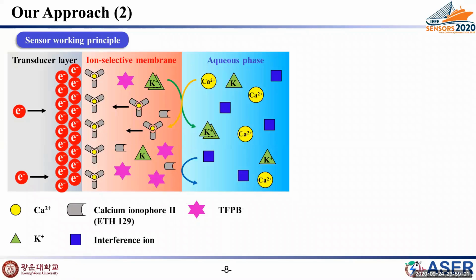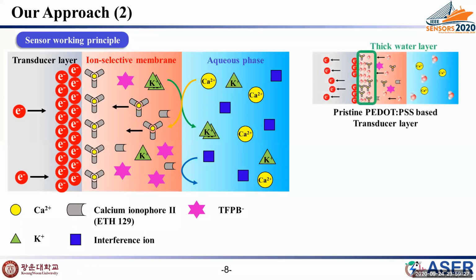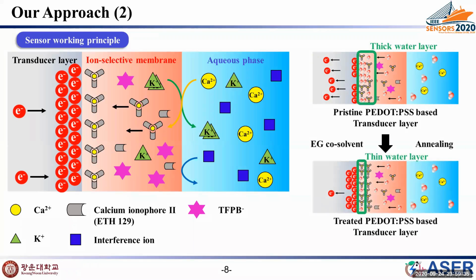I will briefly introduce the working principle of the sensor. The calcium ions in the analyte and the potassium ions in the membrane are exchanged at the interface between the ISM and the analyte. Then calcium ion forms a complex with the calcium ionophore and moves to the transducer layer. At this time, an electric potential is formed across the total ISE, and the potential difference with the reference electrode is output. After that, a water layer gradually forms over time, but this can be suppressed by using our approach, resulting in improved stability with a thin water layer.